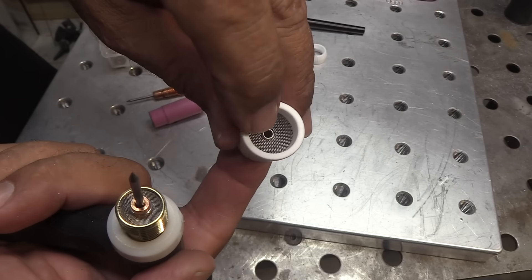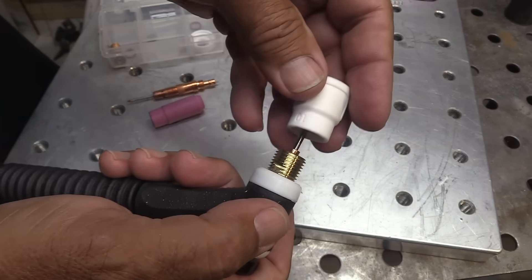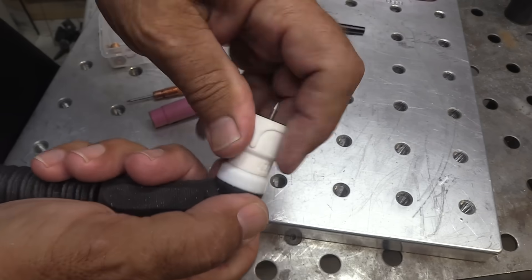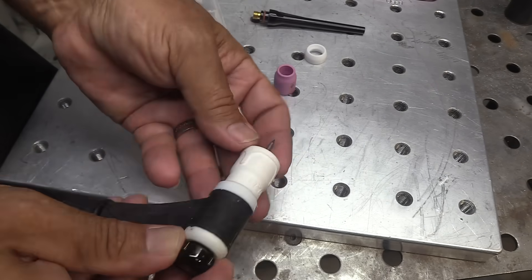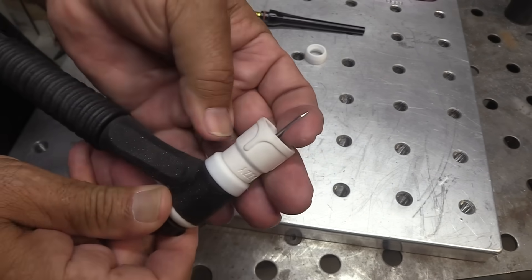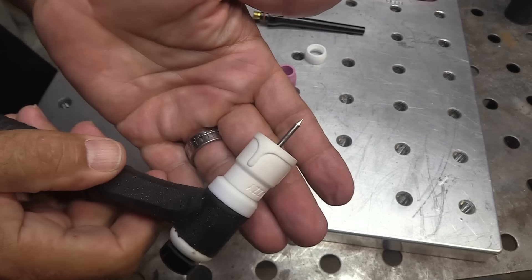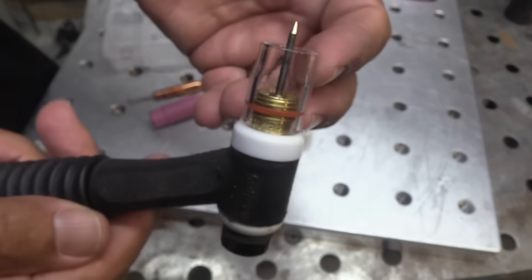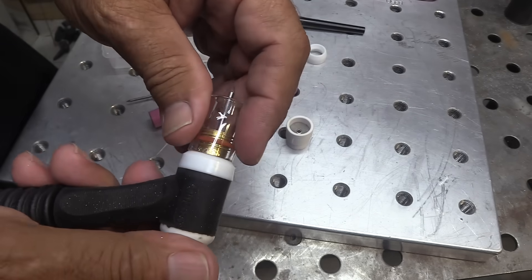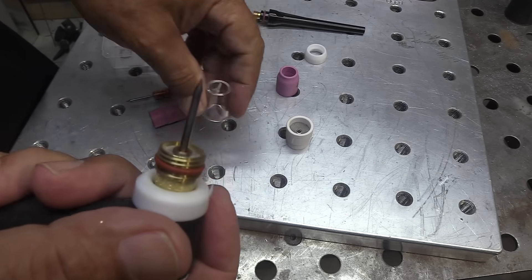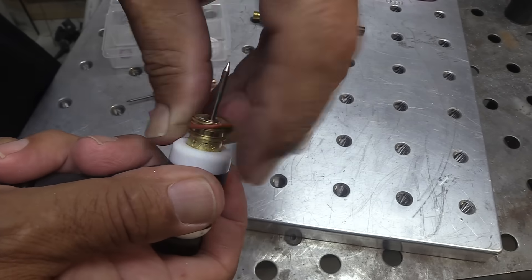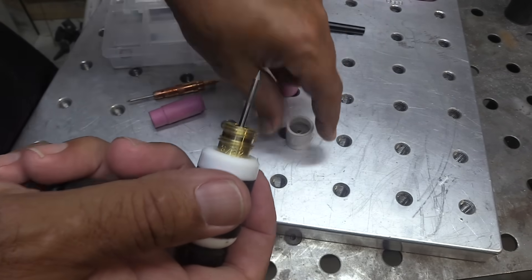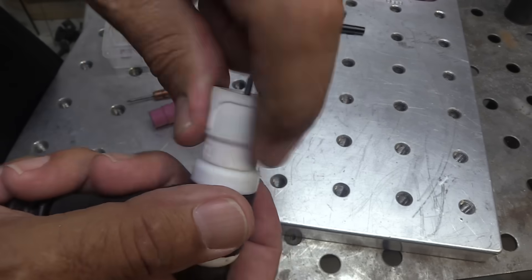And again, the reason is because you got basically two diffusers, two sets of diffusers there, and that just lets you use a crazy long stick out for those times when you need it. And it gives you a nice big blanket of argon, which is going to limit discoloration and also give you a little bit of forgiveness on dipping your rod in and out of the argon envelope.